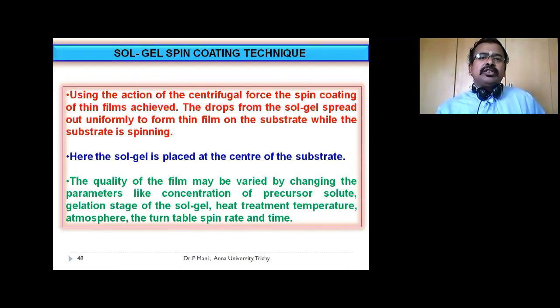Sol gel spin coating technique. Here, using the action of centrifugal force, the spin coating of thin films is achieved. The drops from the sol gel spread out uniformly to form a thin film on the substrate while the substrate is spinning. Here, the sol gel is placed at the center of the substrate.